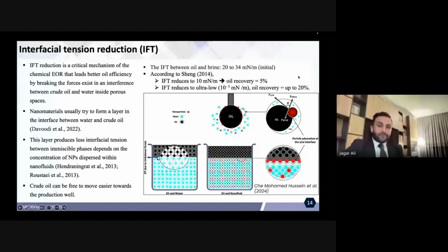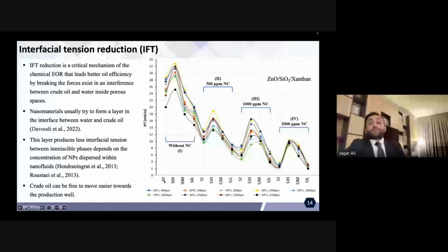So it is reported that the IFT between oil and brine inside the porous media is usually between 20 to 34 millinewton per meter. And then according to Sheng, 2014, when we try to reduce the IFT from the initial value inside the reservoir to 10, then we can increase oil recovery by 5%. And if we reduce it to ultra low values, then we can increase the oil recovery up to 20%. So IFT is one of the dominant mechanisms of EOR which influences and affects the recovery of hydrocarbon inside the porous media.